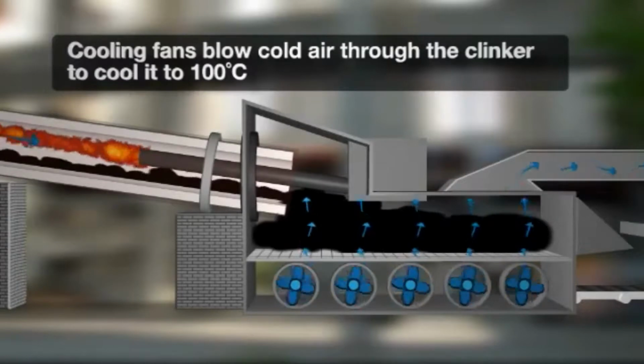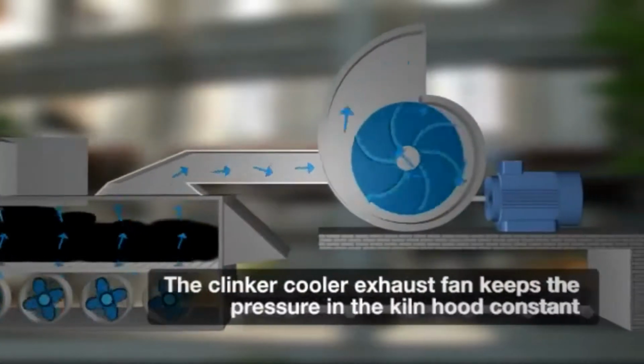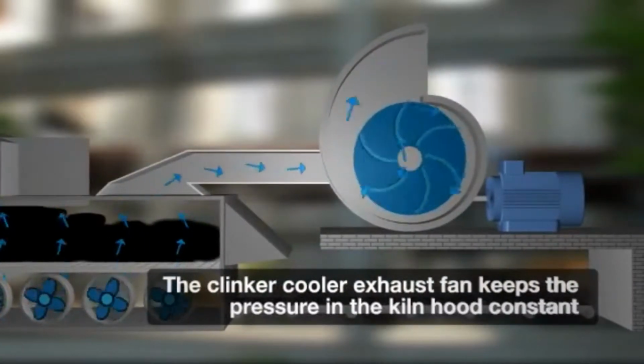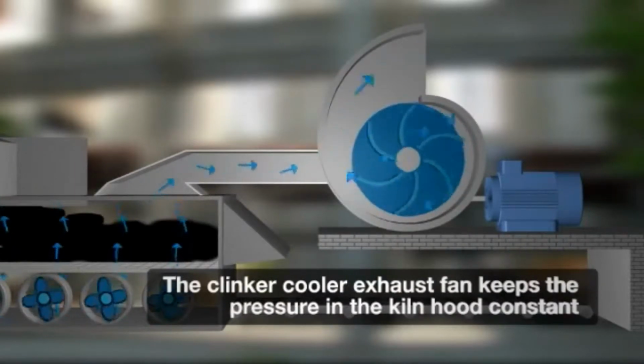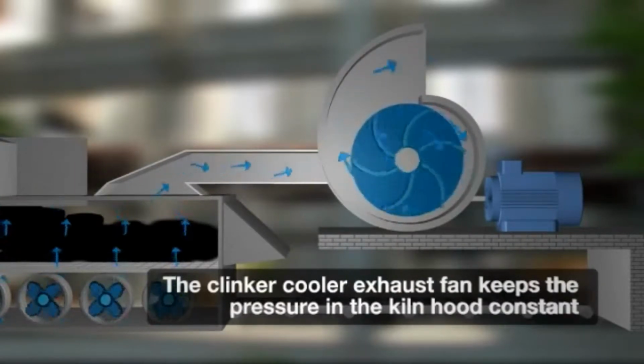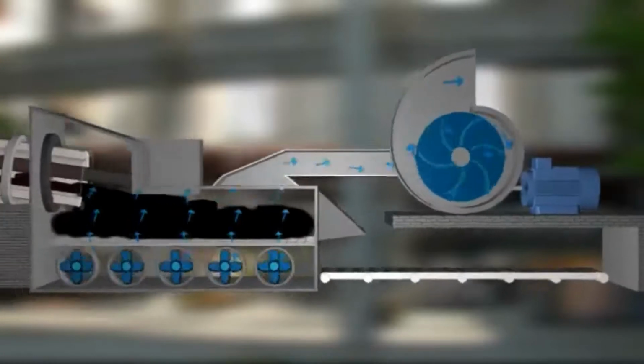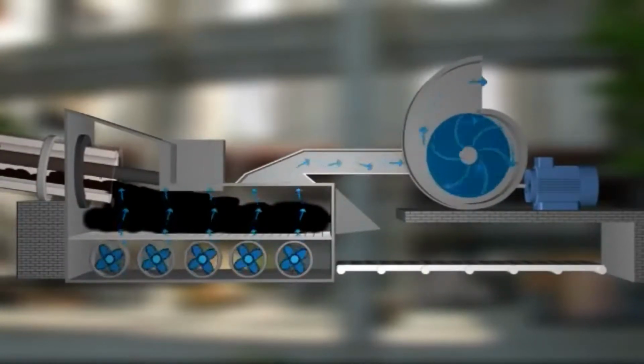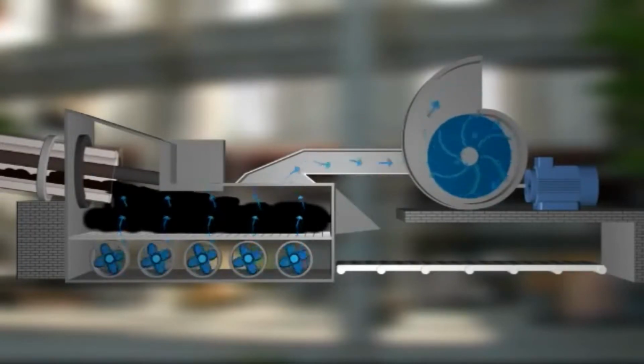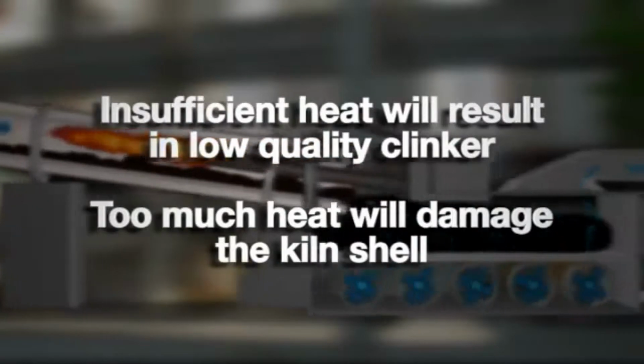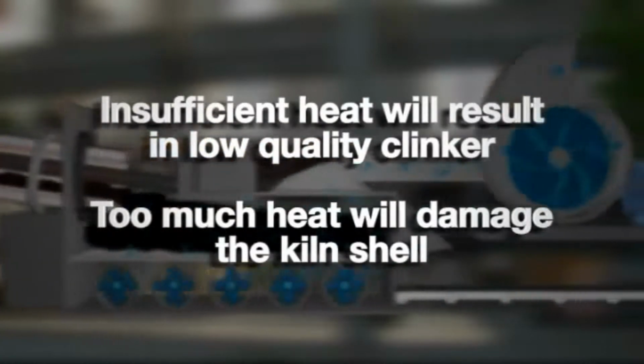By controlling the clinker cooler exhaust fan, the drive keeps the pressure in the kiln hood constant. It does this by regulating the fan speed that draws cold air through the clinker cooler in relation to the hot air that is being drawn through the kiln. Accurate energy input is critical to the quality of cement. Insufficient heat will result in poorly burned, low-quality clinker, whereas excess heat might damage the kiln shell.